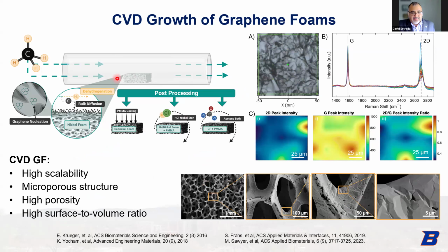We can synthesize this using standard chemical vapor deposition techniques with methane as our source on a transition metal foam substrate. We're using nickel foam in this case. So we do our standard growth at about 1,000 degrees Celsius under methane and hydrogen. Once we have the graphite, it's largely graphitic foam with some tiny regions of graphene when you do the Raman analysis, but we call it graphene foam because that's what the original paper, the primary source, called it. So we then coat that with PMMA, use hydrochloric acid to etch away the nickel, and then we're left with this freestanding carbon foam, right?